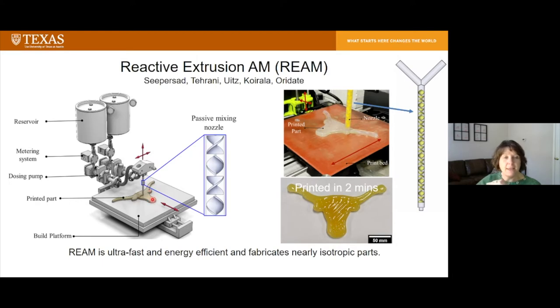And in this case, if you're familiar with standard desktop 3D printers, extrusion-based machines, typically you have filaments of thermoplastic material that melt and are then deposited. In this case, instead of using thermoplastics, we're using thermoset materials. In this case, we're using a two-part epoxy. Those two parts are stored in these two reservoirs, and then they're mixed at the point of the mix manifold. They're combined at the outlet of the mix manifold and then mixed in this passive mixing nozzle.